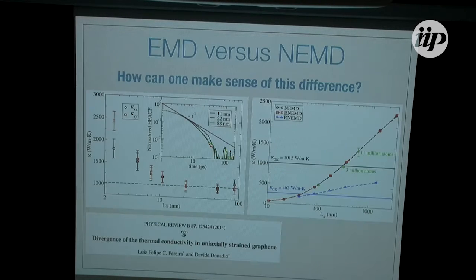Now, this is a good result in a way because graphene is supposed to be this super ideal two-dimensional material, and we were getting experimental or simulational results that were exactly what you would expect for an ideal two-dimensional system. On the other hand, we had these really good equilibrium molecular dynamics simulations that showed a finite value for the thermal conductivity regardless of system size, right? So we had to make sense of what was going on. One of these results was wrong. We didn't know which one.